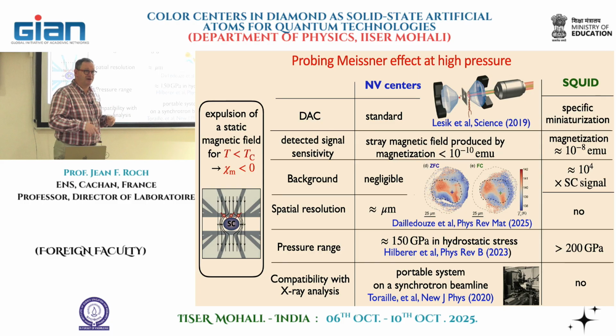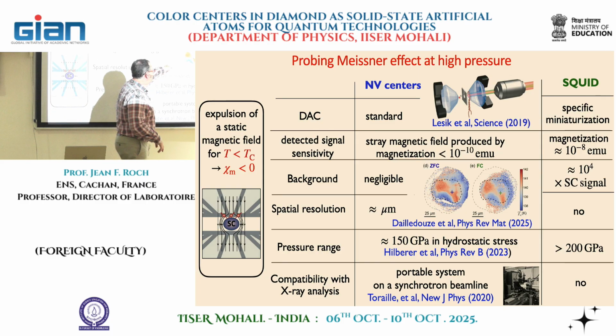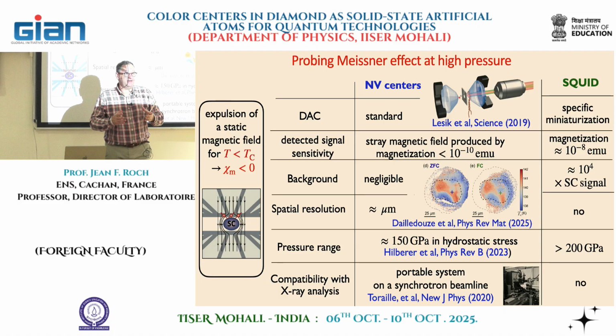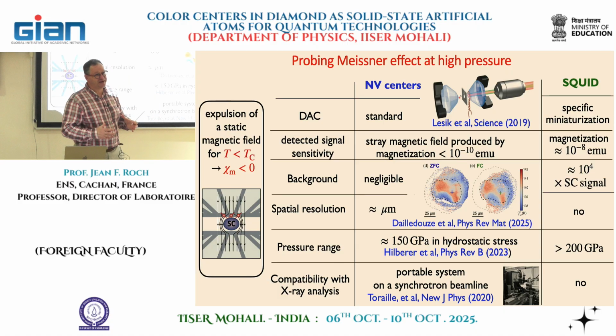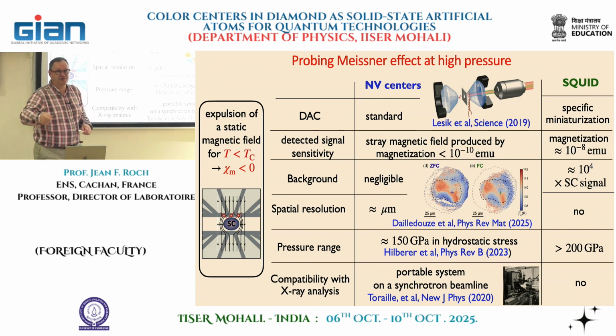But more than that, what we can do is really map the critical temperature. So we can deal with inhomogeneous samples. That's something quite important. As soon as you apply pressure, you can imagine that there can be inhomogeneities created in the materials. Or even if you get the materials from a chemist, they will certainly be non-perfectly homogeneous.